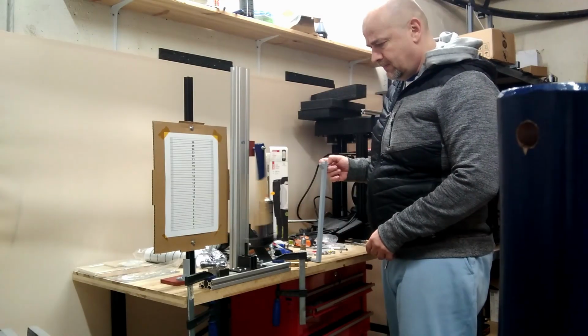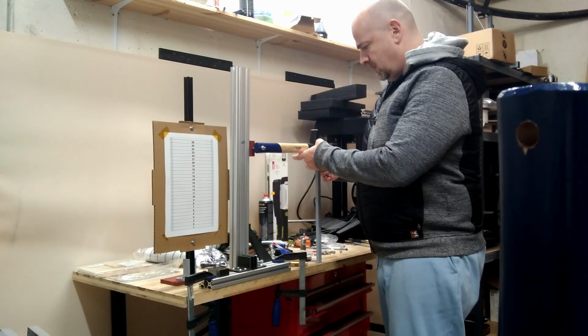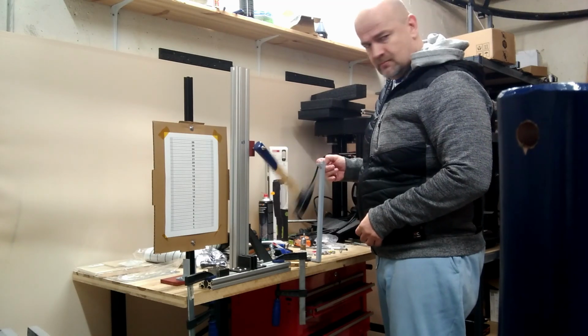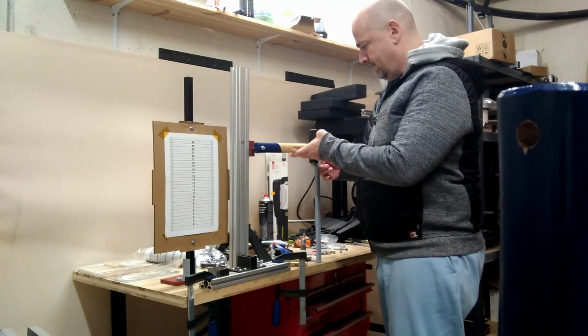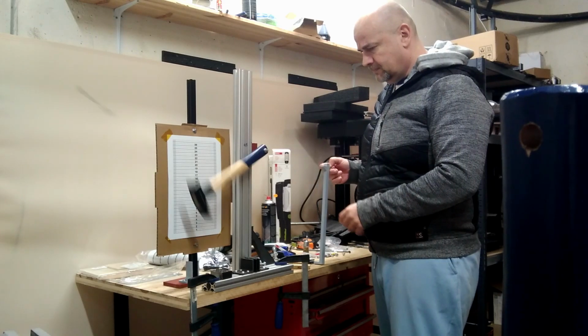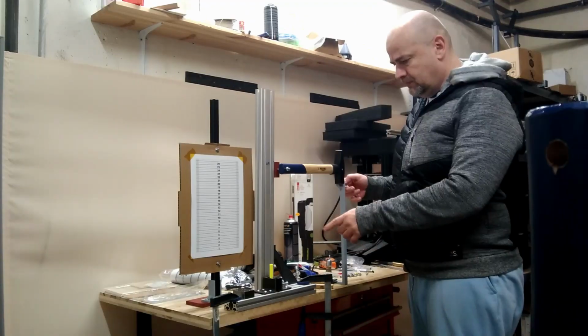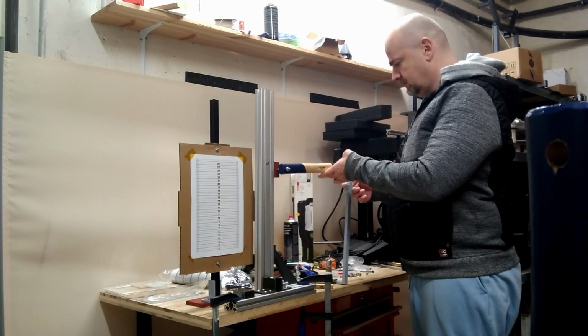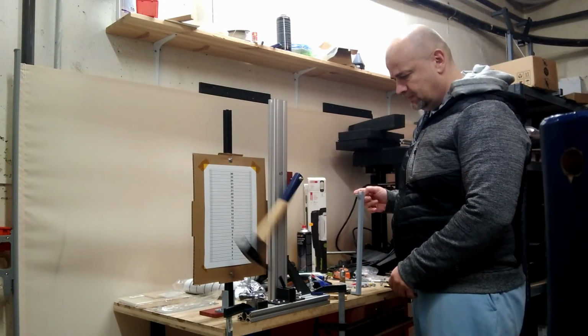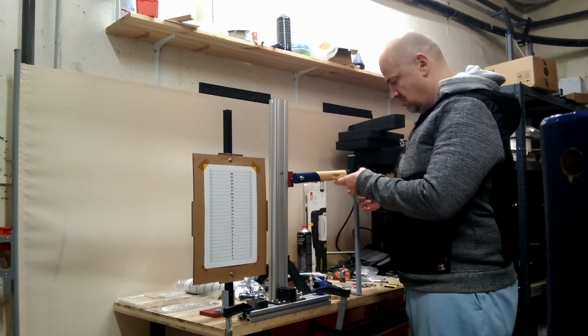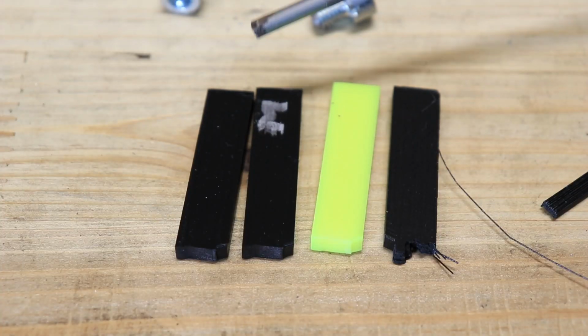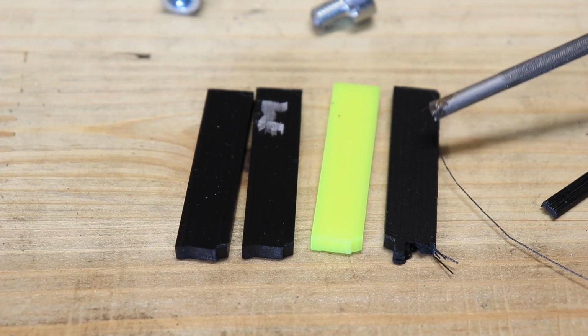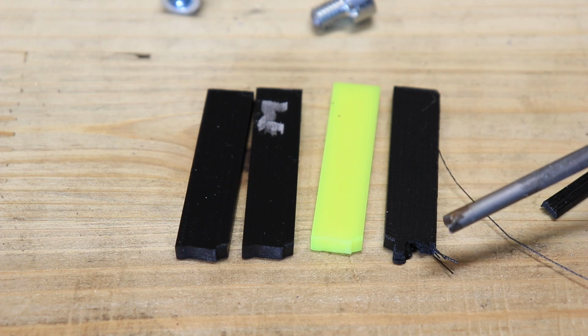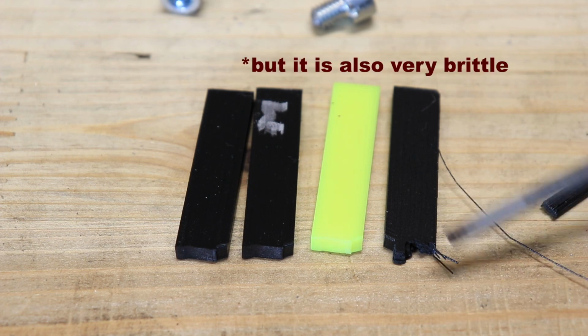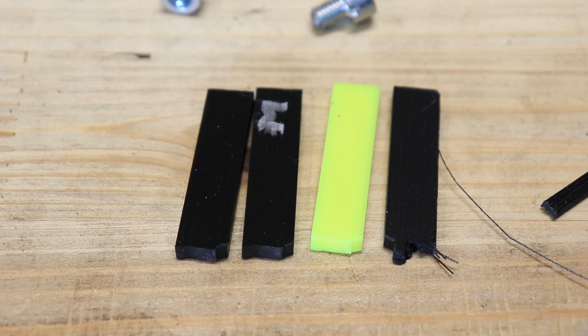Regular PLA, 0 position, PLA META, PLA plus, carbon PLA. These three broke very similarly, they are very brittle materials, but the carbon fiber version didn't break in the first hit, only when the hammer swung back, only then it broke off the remaining part. But now let's analyze the footage.